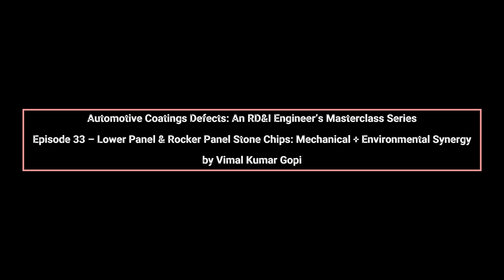Environmental exposure dramatically amplifies damage progression. Once a stone chip penetrates the coating stack, bare metal or weakly protected primer is exposed. Water, road salts, and contaminants rapidly infiltrate the damaged area, initiating corrosion beneath the surrounding intact coating. Freeze-thaw cycles expand trapped moisture, widening cracks and accelerating delamination. This is why stone chips on rocker panels evolve into corrosion much faster than similar damage on higher panels.